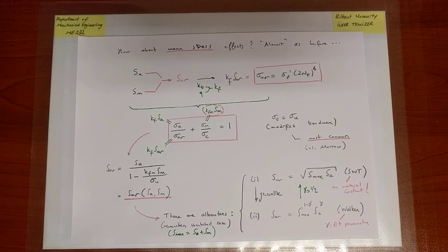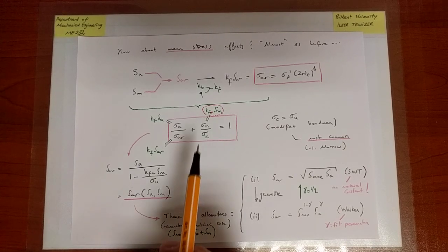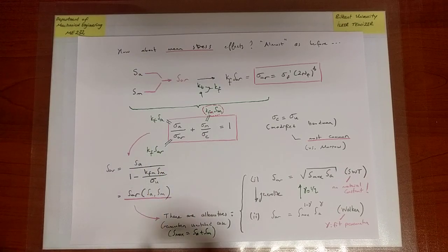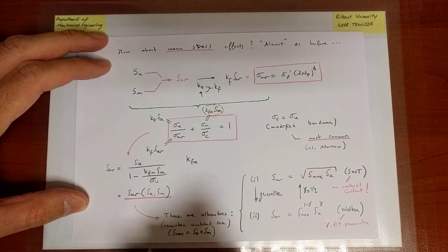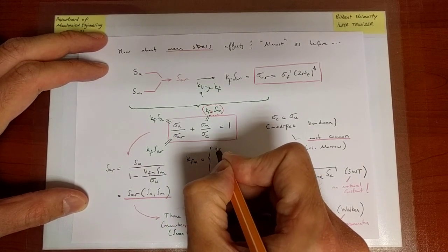Let us now proceed and demonstrate the idea of working with notched members through an example. And the last piece of information that we need for this purpose is the possibly different value of KFM with respect to KF. And indeed, the convention dictates that KFM, in other words, the fatigue notch factor for the mean nominal stress, is equal to Kf